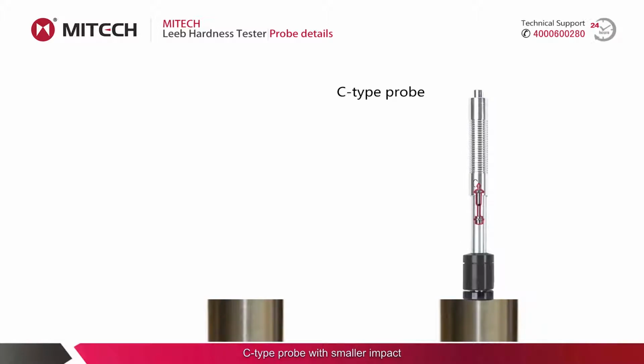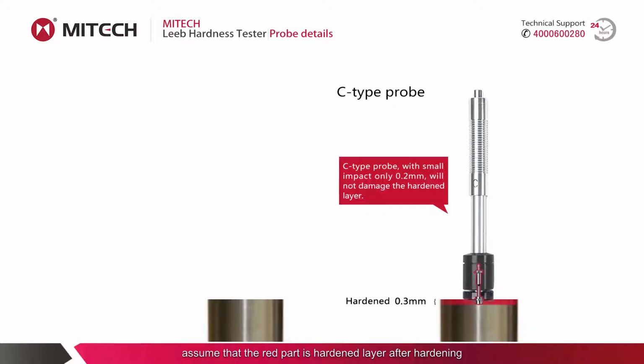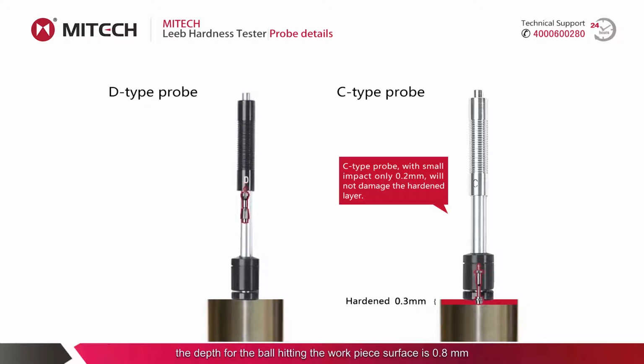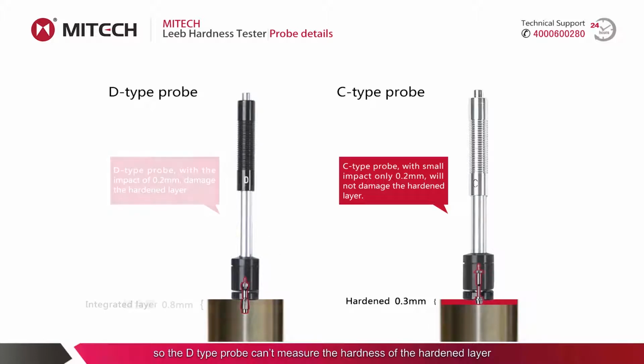C-type probe has a smaller impact, so it causes less damage to the measured surface and does not damage the hardened layer. It is suitable for measuring small, thin workpieces and surface hardened layers, as shown in the figure. Assume that the red part is the hardened layer after hardening, all within 0.3 mm. But with the conventional D-type probe, the depth of the ball hitting the workpiece surface is 0.8 mm, so the D-type probe can't measure the hardness of the hardened layer.